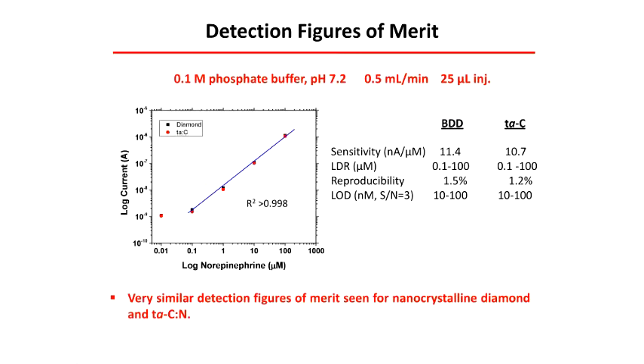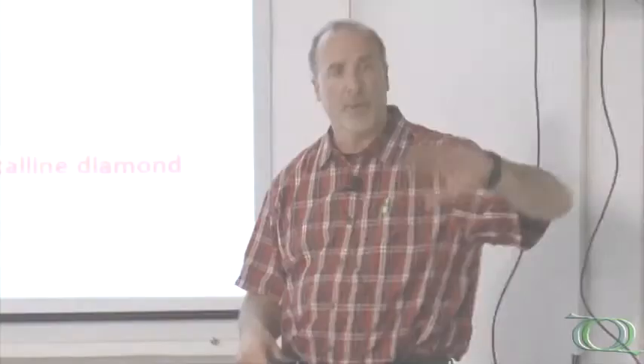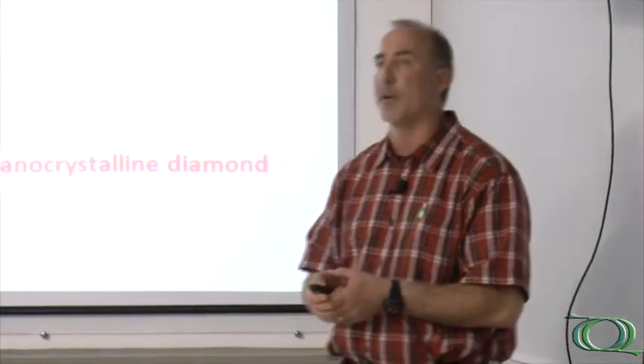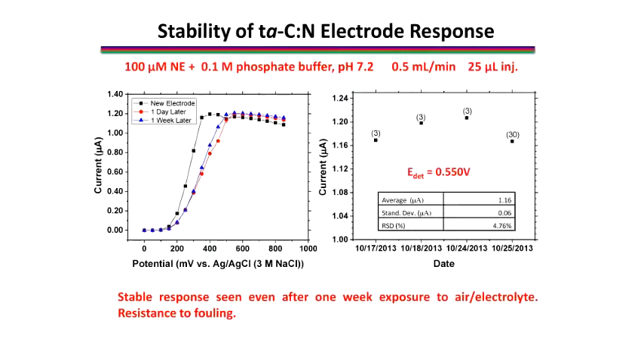Our detection limits, depending upon the electrode, are between 10 and 100 nanomolar. Reproducibility for both electrodes — the ta-C and the diamond — are very, very good, about 1%. Dynamic range is typically the same for both of them, and the sensitivity, the slope of the response curve, is the same for both. So diamond and ta-C behave almost identically in these electroanalytical applications, and these ta-C materials look like they have very good capability for analytical applications.